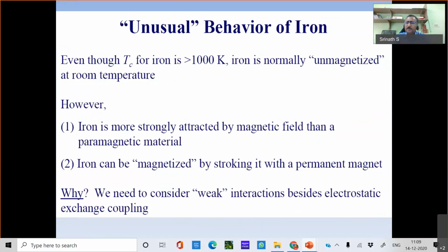I'm sure most of you know, but it's important to understand once again that if you see iron, the TC is 1043 Kelvin. In fact, it's greater than 1000 Kelvin. But if you see a nail on the road, most often this material will be non-magnetic. It will not show any magnetic property. It will not show any attractive property, right? So why is that? Even though TC is much higher, that means it should have been ferromagnetic. Why is it not showing any magnetization?